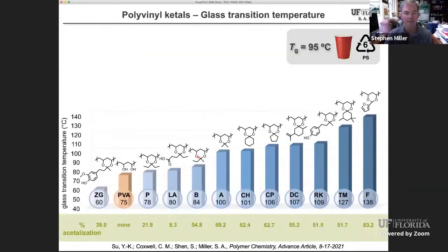And this does, in fact, change the properties quite a bit. You can see here in the middle, with acetone in the middle of this plot, it gives us a glass transition temperature of 100 degrees. So we're pretty excited about that because the Tg essentially matches or slightly exceeds the Tg of polystyrene. And it's a comparably inexpensive material made from polyvinyl alcohol and acetone. Two things that are fairly inexpensive, maybe slightly more than polystyrene itself, but nonetheless in the same realm for its economics.